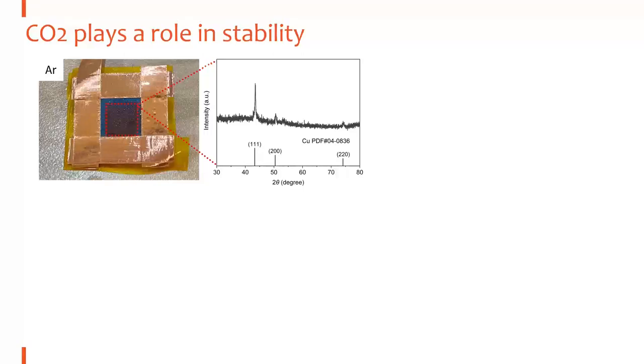What's the reason? This came from something going wrong, because the students, when they tried to do the CO2 reduction, used argon instead of CO2. So they did not observe any products, which is obvious because they don't have CO2. But when they disassembled the cell we use to measure the performance, they found that the material changed from dark blue to dark red under argon atmosphere. When we put the catalyst into XRD, they found the typical peaks for copper 111. That means under argon conditions, the copper BTA molecule is not stable. It turned out to be metallic copper.